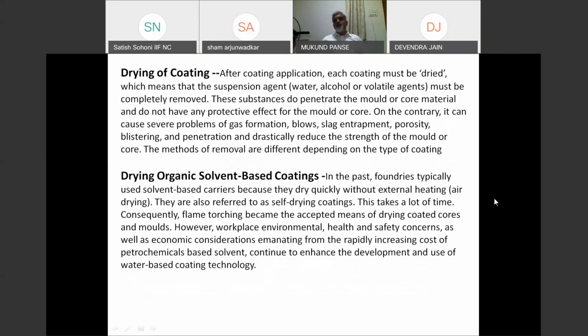After the coating is applied, the question comes for drying. After coat should be dried properly, suspension agent completely removed. The substance do penetrate mold and core material, but ensure that it doesn't affect the core and mold original strength of the hand. It doesn't become friable. The gas formation, slag entrapment, etc. do not happen. The organic based carriers, they get slightly heated and burned properly. The problem only comes mainly with water-based paint coating.